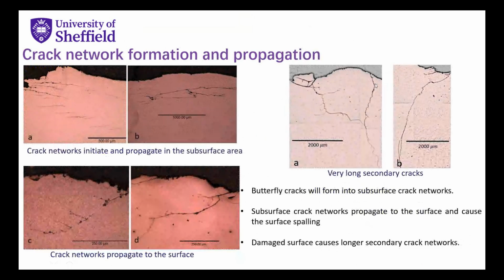And the second stage of the rolling contact fatigue is related to crack propagation. So when we have the fatigue cracks propagate from these small inclusions, they may connect with each other and form into very long subsurface crack networks, as shown by picture A and picture B here. They are all subsurface cracks. And if these subsurface cracks propagate to the surface, it will cause spalling on the surface, and accelerate the failure of the bearing, as shown by figures C and D over there.